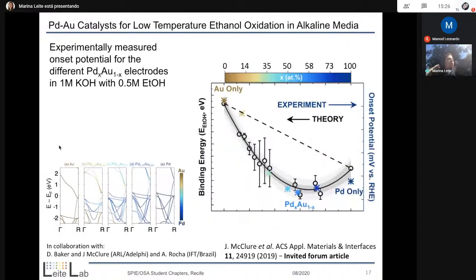Now, we also moved on to look into other types of metals, for other types of applications. In this case, this is a collaboration with the Army Research Lab, Josh McClure, and again, Alexandre at IFT Brazil, where we're looking at palladium gold for catalysis, specifically for low temperature ethanol oxidation. So again, you can see here the DFT was very handy for us. In this case, I find it really neat that you have pure gold, and now we're looking again at the gamma point. Once we add a tiny bit of palladium, you can see how you change completely the valence band of the material. This is really interesting in this particular case, to see the breaking degeneracy of these bands. And just one example of an overall result here, look at the binding energy as a function of chemical composition.